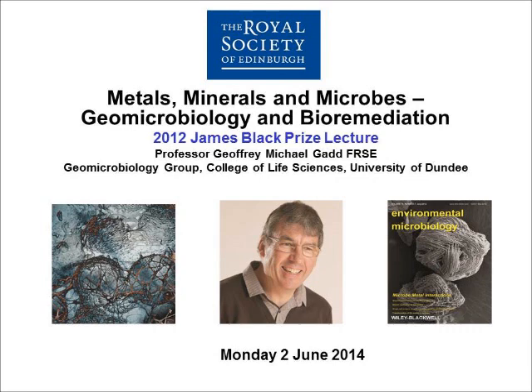mechanism. But why this is important is that this is going on in the environment as well, and a lot of these other things, all these elements can be associated with these kind of ores. So if you get this in the environment, you can get some kind of acid mine drainage or leakage or something like this, even from landfill sites, that might contain lead or cadmium or arsenic, for example. In growth, the fungi can even take up the particles from solution, and you can see them here. They've completely absorbed the particles from solution. But they'll also release zinc, in this case, into solution, and this just reflects the zinc going up to about 20 mg per litre, about 0.3 millimolar, so that's quite a high concentration.